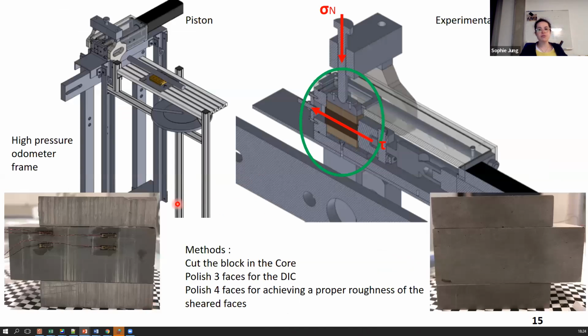So 3 rectangular blocks are cut in a core of Cox claystone. The dimensions of the blocks are set on the diameter of the core provided by Andra. And from now on, I will refer to the 3 blocks as one sample. We shear the central block between the 2 upper and lower blocks, which are blocked at their ends, so both blocks here are blocked there, and we push here. That allows us to avoid having to manage a contact between the rock and the frame. That's why we are shearing 3 blocks and not 2 blocks.